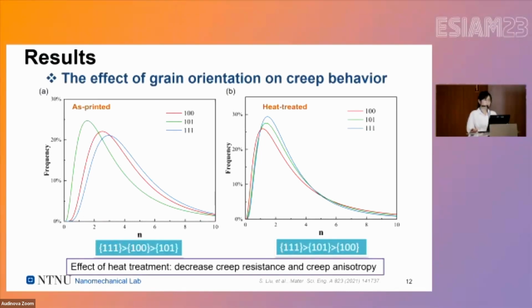And we found that the N values in the heat-treated sample are smaller than in the printed one. So we can conclude that the heat treatment decreases the creep resistance and the creep anisotropy.